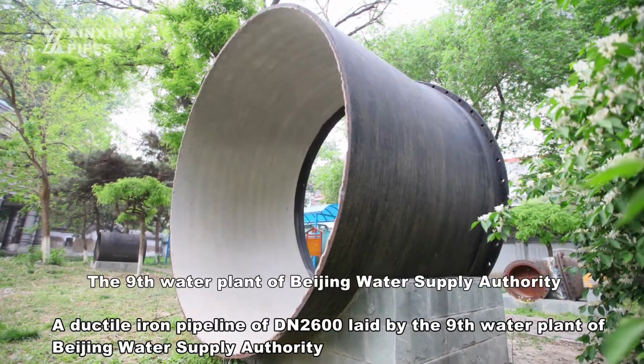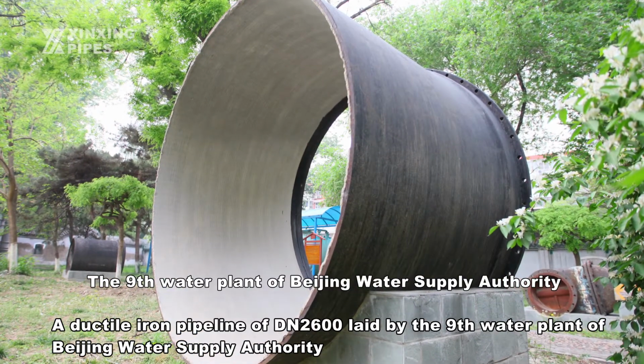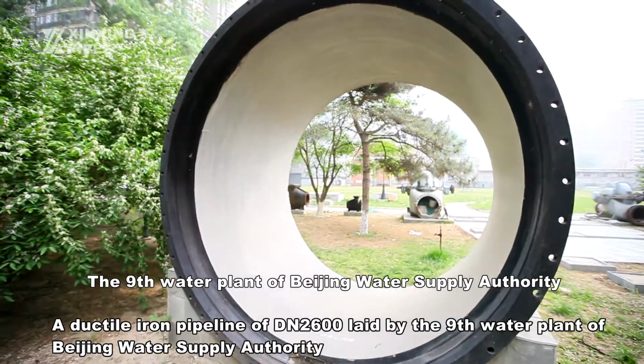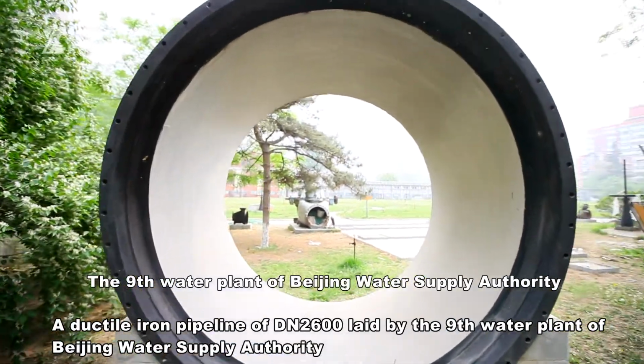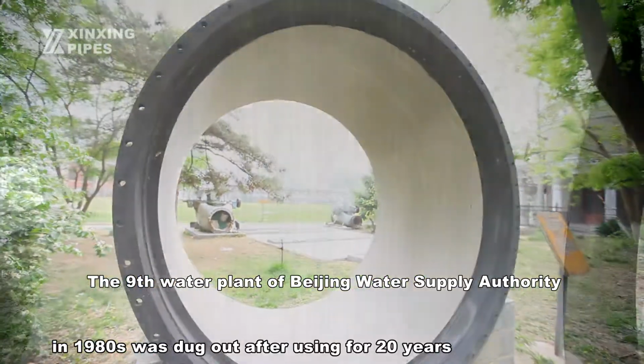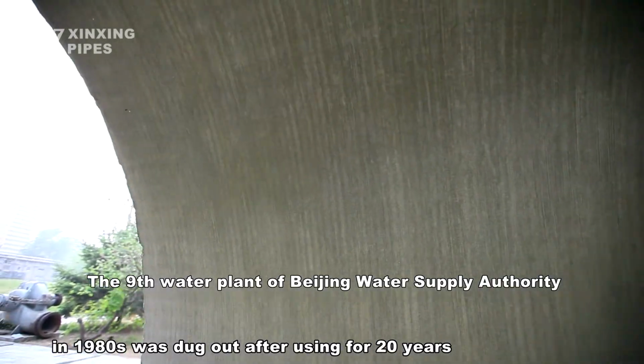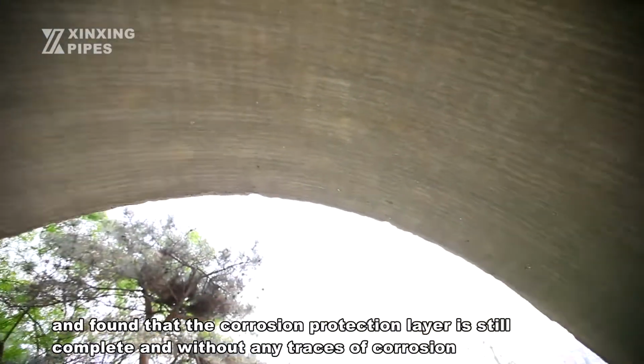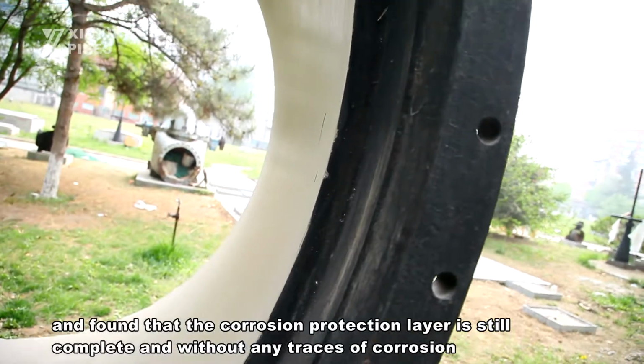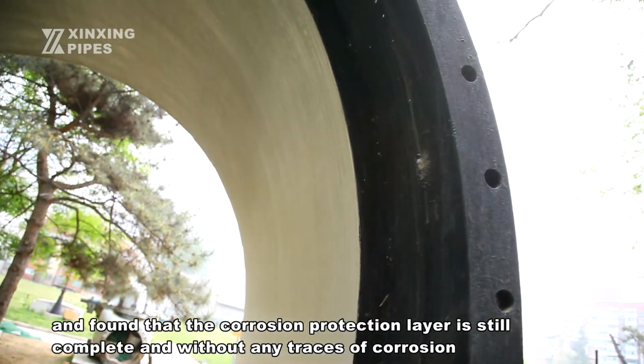A ductile iron pipeline of DN2600, laid by the 9th water plant of Beijing Water Supply Authority in the 1980s, was dug out after being used for 20 years, and the corrosion protection layer was found to be still complete and without any traces of corrosion.